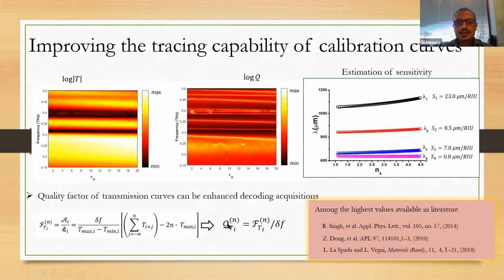This algorithm basically provides an enhancement of the quality factor of each resonance that follows, in any case, the maximum, so it's a reliable process. And now we engineer the quality factor of this resonance, and we can push down the width of each resonance to a few points in the frequency domain, so extremely high. Now, applying this process, we can see here the log of Q, and we have a very clear dynamics of the frequency of the transmission peaks, so we can trace them out.